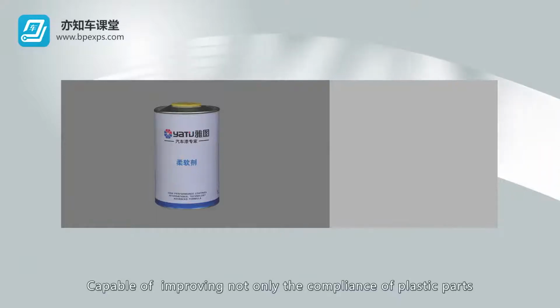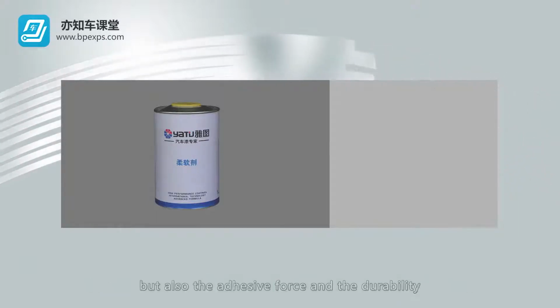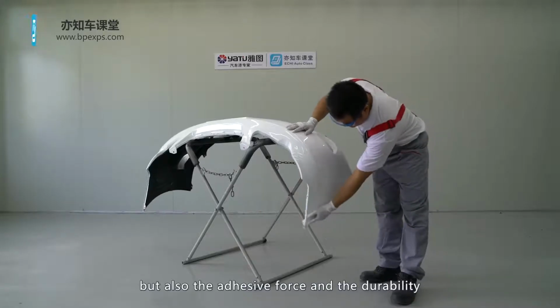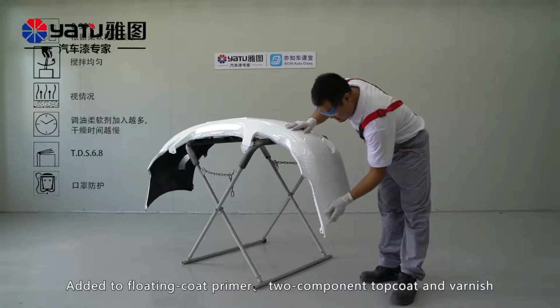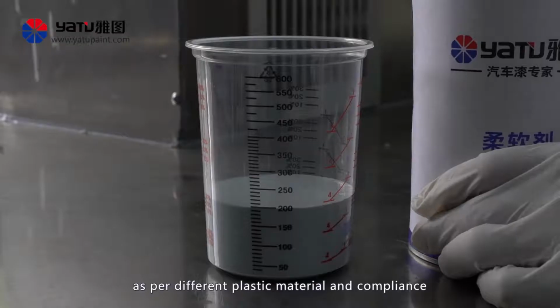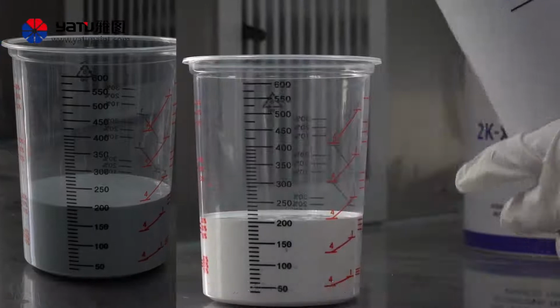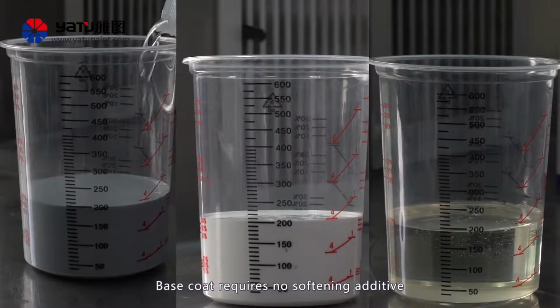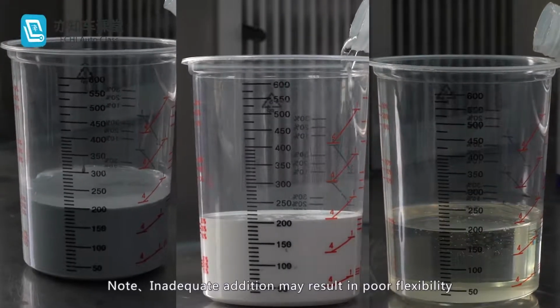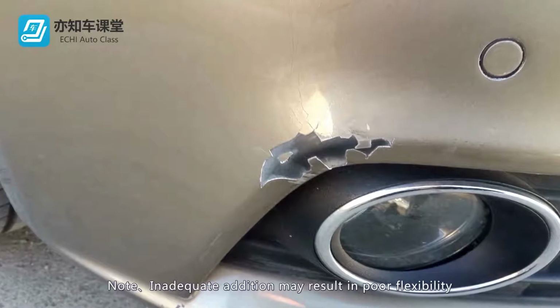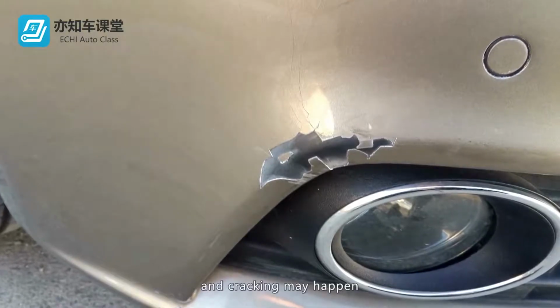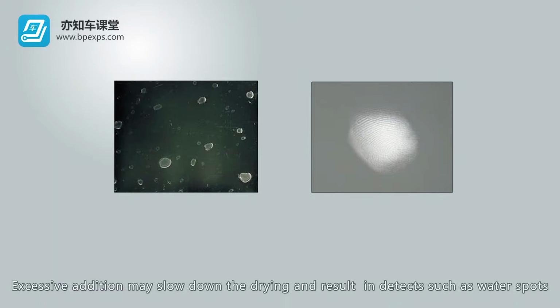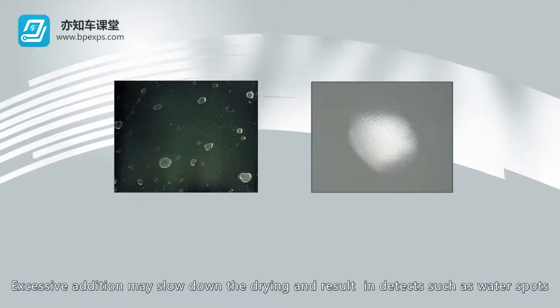Softening additive, capable of improving not only the compliance of plastic parts, but also the adhesive force and the durability, added to floating coat primer, two-component top coat and varnish as per different plastic material and compliance. Base coat requires no softening additive. Note: inadequate addition may result in poor flexibility and cracking may happen. Excessive addition may slow down the drying and result in defects such as water spots.